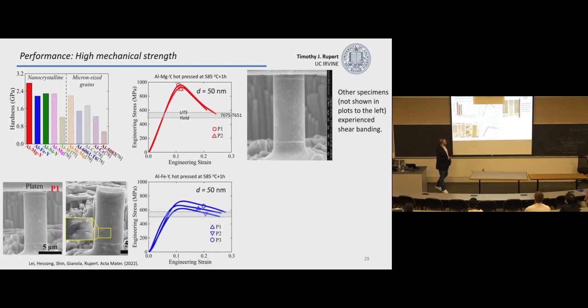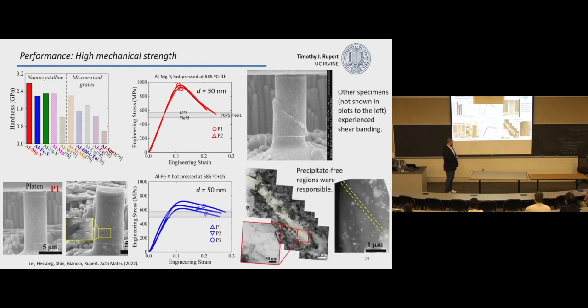There are some interesting complications. Sometimes in these micropillars, when you do the compression, you can get a shear banding type of deformation. We've actually studied this and found that it has to do with the distribution of some secondary intermetallics you get inside of your material. And if you don't have a pathway that's free of those intermetallics, you can have the development of a shear band, which coarsens your microstructure and destroys it.